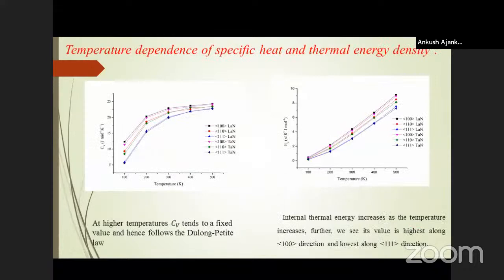The specific heat and thermal energy density have been evaluated using the integral involved in the Debye theory of specific heat, and the obtained values of specific heat and thermal energy density are in good agreement with the values obtained from the theta D by T table of the AIP handbook. From the plot, it is clear that at higher temperature, the specific heat tends to a constant value, hence obeying the Dulong-Petit law, while the internal thermal energy increases with the increase in temperature.